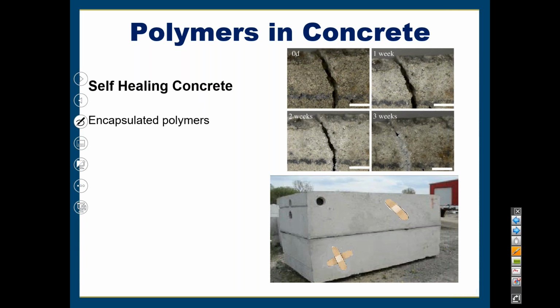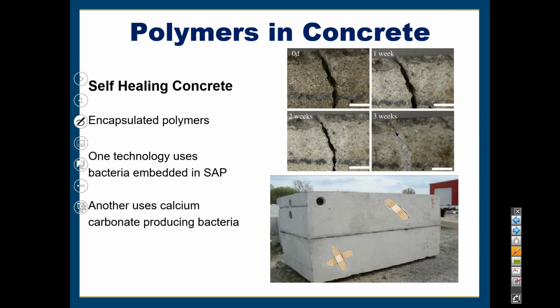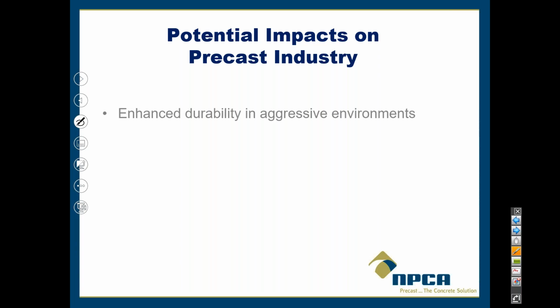And that can be done either through encapsulated polymers. So when the encapsulation is broken, it releases a material that fills the crack. There's a technology that uses a bacteria, an actual bacteria that is embedded in a super absorptive polymer. And when it's released, it releases material to fill in the cracks. And then others use calcium carbonate producing bacteria that do the same thing. So that's basically the essence of self-healing concrete. And a lot of these technologies use polymers. So polymers can really be helpful.